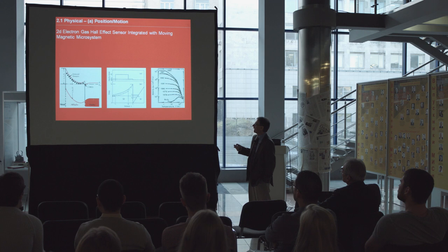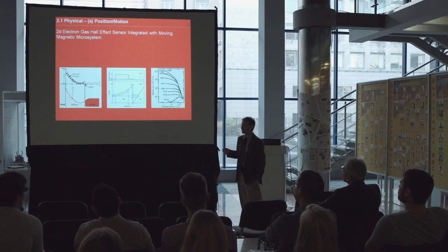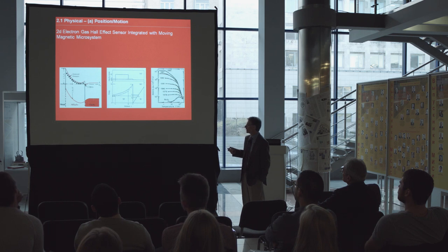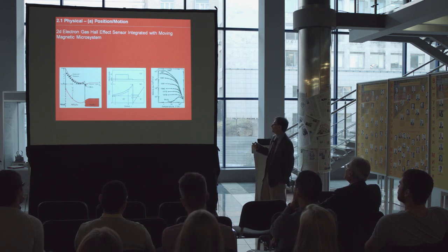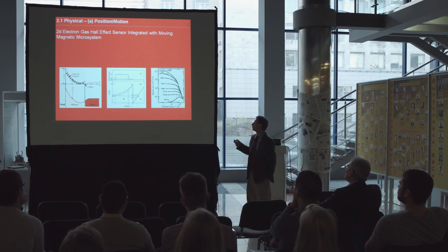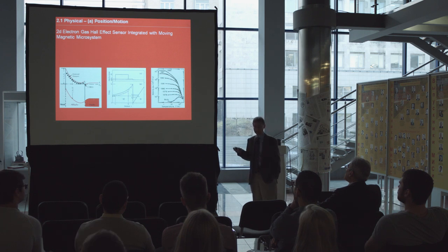And so the idea is to harness something called a two-dimensional electron gas. The structure is shown on the left here, and I'm going to talk in detail about that. The reason we look at this structure for these particular sensors is because this two-dimensional electron gas is imbued with extremely high carrier mobilities. That's the carrier mobility, and the numbers here refer to, for example, the record I'm showing for 1989. A group we work with in Cambridge is at around 10 million, in fact now almost 20 million centimeters squared per volt second.